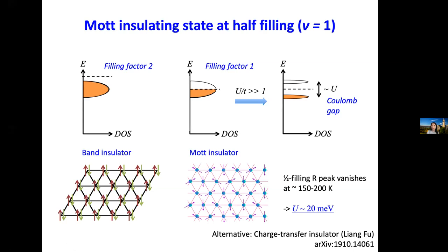We can estimate the parameters a little bit from this measurement. The half filling of the band, the one particle per site peak, vanishes at a temperature around 150 to 200 Kelvin. That gives us a lower bound of the on-site Coulomb repulsion to be about 20 meV.